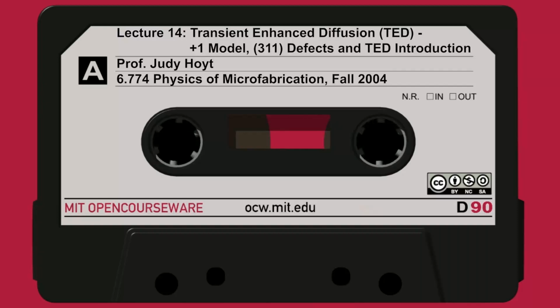That's a high dose. And so you can see, this should say 0 minutes. I'm not sure what happened to the 0, but anyway, this means when you're close to starting, what you have is an amorphous layer from the surface down to some depth. And in fact, here's the scale bar. This is 100 nanometers from here to here. So that's maybe 300 nanometers, 3,000 angstroms deep, something like that, is all amorphized. The crystal structure is completely destroyed. You have an amorphous solid.